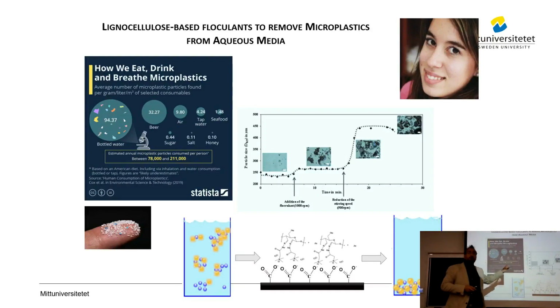Something totally different. Now this lady, she was in Sundsvall recently, and she's working on developing cellulose-based derivatives for microplastic flocculation. We know that microplastics are everywhere. We know that they are eventually bad. We don't know how bad they are at this stage. We don't know their real impact so far, but we know that perhaps it's too late. It's not too late, but before it is too late, it's better to do something at this stage. And what we are trying to do is to develop these novel cellulose-based flocculant agents that we can then use to aggregate the microplastic particles, getting bigger aggregates, and then eventually they will either sediment, or we can easily remove them with filtration, and they don't end up in the rivers or oceans.